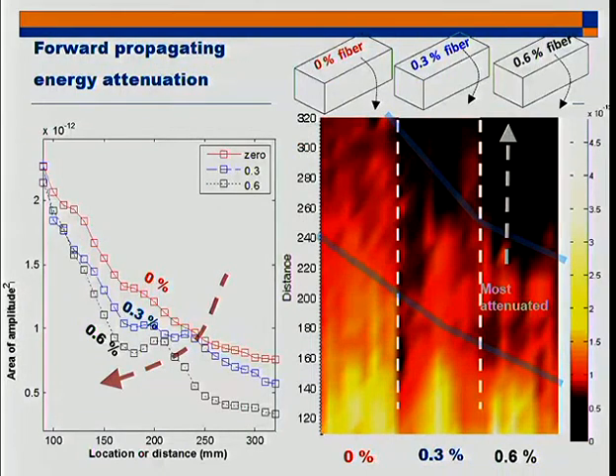and that if we do all the right processes, we can differentiate between different levels of distributed damage in a material. So 0% means concrete with no damage in it, and 0.6% means higher internal volume of defects, simulating fracture. So we can see these lines of increasing attenuation. So more damage means more attenuation, lower amplitudes, because the damage is absorbing some of that energy. And we can see that graphically here too. But it's also pretty clear that there's not great distinction between those three damage cases.